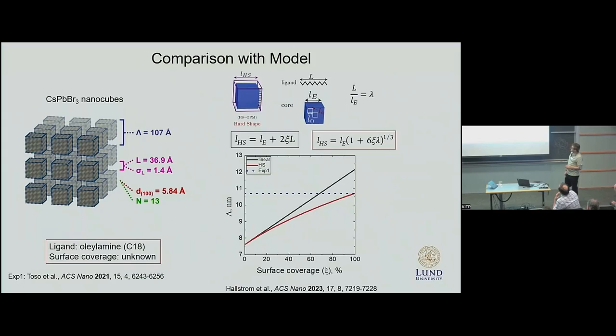First, looking at nanocube superlattices with oleylamine, oleylammonium ligands. In this case, we don't know the surface coverage - we just didn't bother to quantify it. What we know is that the way we treated our nanocrystals empirically would probably result in a high surface coverage percentage. So the predictions of two models: one with hard surfaces with a polymer brush in between, and the second, sort of soft nanocubes.